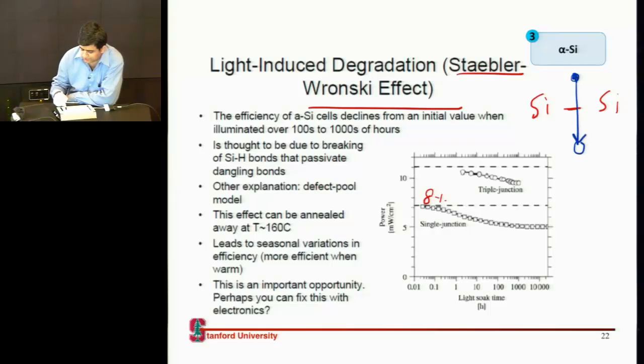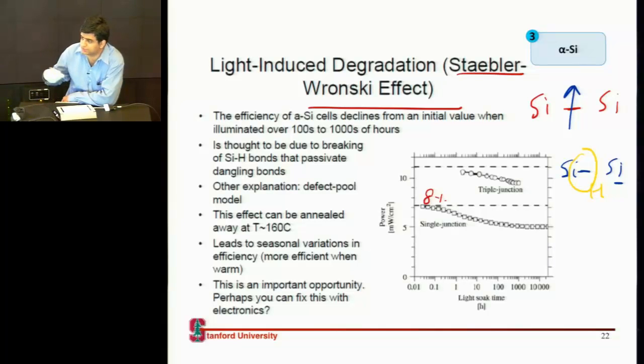And these electron and hole pairs, when they recombine, they give away this energy either to a photon or they give it away to the lattice, right? So when they give this energy to the lattice, this bond essentially breaks, right? So this bond between these two silicon atoms breaks, and it creates two dangling bonds, one on each of these silicon atoms. Now, a hydrogen atom can come in and it can passivate one of these dangling bonds, but still at least one dangling bond among these two atoms would be unpassivated, right? So when you shine light on these materials, you'll just keep on generating more and more dangling bonds. So if you take the cell, you measure its efficiency right when it came out of the lab, it would be something.